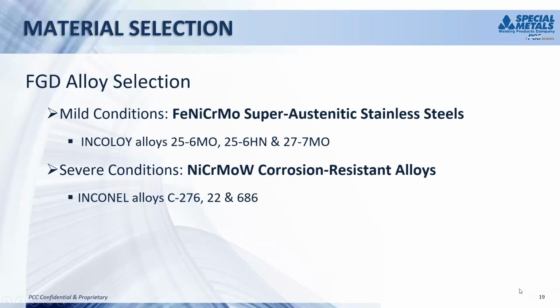have been used. These are the superaustenitic stainlesses that are modified with nitrogen. They typically contain about 6% molybdenum, and we make 2 of them. One is called Nickel Alloy 25-6MO, and the other one is 25-6HN. We also developed an advanced grade of superaustenitic stainless that's called Nickel Alloy 27-7MO.